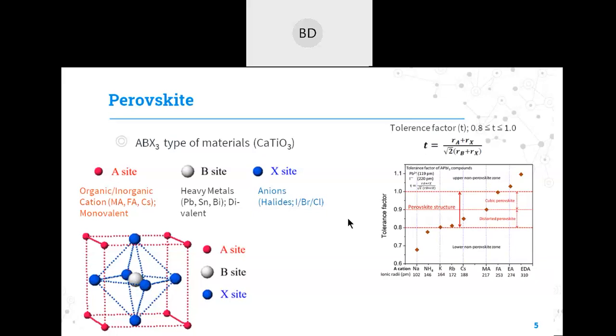To make a good perovskite, or a perovskite of optoelectronic quality, we have to take care that the perovskite tolerance factor should be between 0.8 and 1. This is the range where the perovskite is optoelectronically active. So if you choose the radii of the A, B, and X side ions, which govern the tolerance factor, it should be between 0.8 and 1, and for better performance it should be between 0.9 and 1, which is the cubic phase of the perovskite, the most symmetric phase. So if you are changing the cation or anion position, it should not differ from this range.